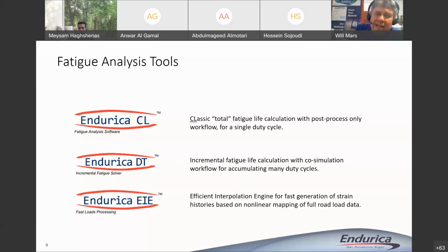And if you try and take that 2 million time steps and directly feed it to a finite element model, it's not going to solve, because it'll just be too much information. But with the EIE tool, what we do is we can take the road load data and we can convert it into stress strain history to use in fatigue analysis. And it's an interpolation based method. So we pre-compute a small number of representative states of the part, and we interpolate between them to very rapidly generate strain history. What's nice about this is it does allow you to capture rubber's nonlinearity, and it's also extremely fast. It's like 10,000 times faster than running a finite element model.